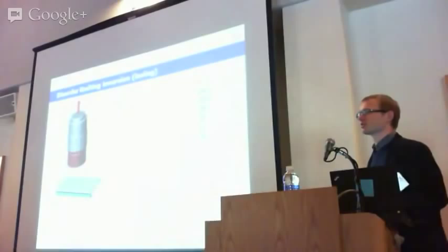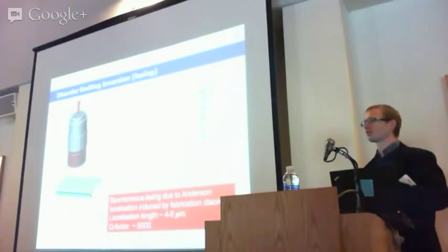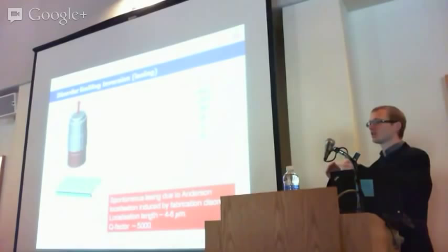You can extract this from the localization length. If you like lasers, you don't know where they are. So it actually doesn't help just to be very good at fabrication. Of course, it does help to some extent, but the better fabrication you do, the more well-defined band edges you actually have, so a very small defect will then give you a fairly high Q cavity. So this is something you have to worry about if you want to do these kinds of amplifiers.